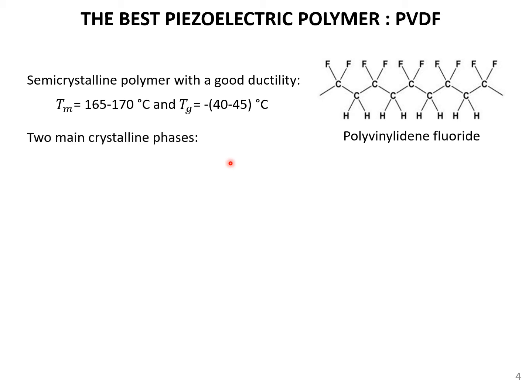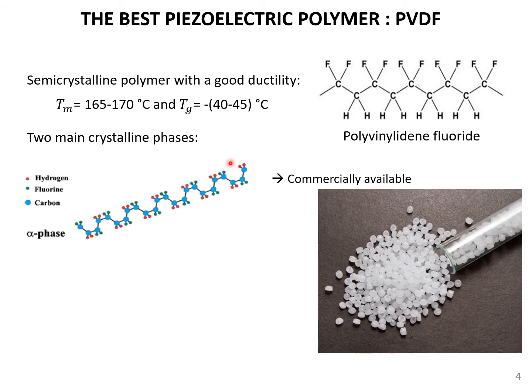If you look at the crystalline phase of PVDF, there are two main phases. The alpha phase, this is the common phase that you obtain after processing PVDF, and this one is non-piezoelectric because all the fluorine are in the opposite position from the hydrogen along the backbone of PVDF.